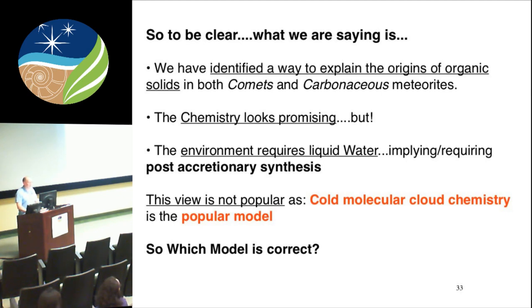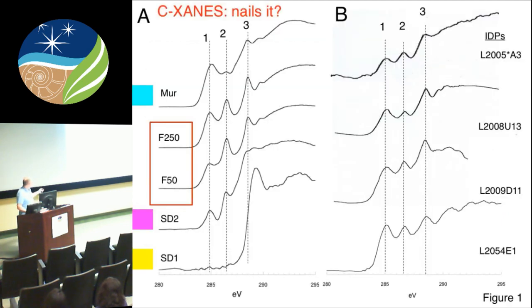with the NMR better, but when you look at the XANES, there's a significant difference. Is a group 2 of any significance in what you're seeing here? So XANES is very subtle. While these look superficially very similar, in fact, the relative intensity of this aromatic carbon is about a factor of 2 of this. So actually, XANES essentially hides a lot of the chemical complexity that NMR does. You would always rather do NMR if you could do it. But with these tiny little stardust particles, the only game in town is XANES.